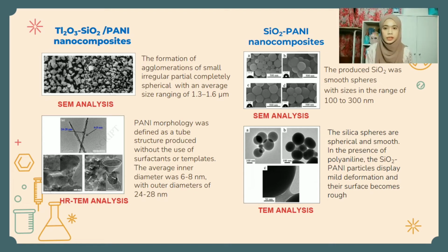The same analysis for silicon dioxide polyaniline nanocomposite showed that the produced silicon dioxide was smooth spheres with the size in the range of 100 to 300 nanometer. For the TEM analysis, the silica spheres are spherical and smooth. Moreover, in the presence of polyaniline, the silicon dioxide polyaniline particles display mild deformation and their surface becomes rough.